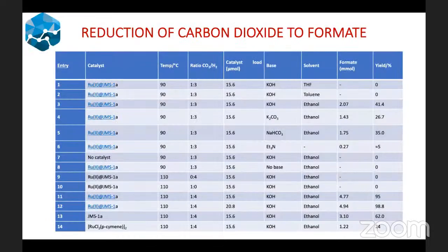We then applied our MOF in heterogeneous hydrogenation of carbon dioxide to formate. In this table, it shows different entries and reaction conditions that were used in the hydrogenation of carbon dioxide to formate. For example, entries 1, 2, and 3 show the effect of the solvent on the formation of the product formate. At 90 degrees, a pressure ratio of 1:3, that is carbon dioxide to hydrogen, and a catalyst load of 15.6 micromole, if you have THF as a solvent, you don't get any product.